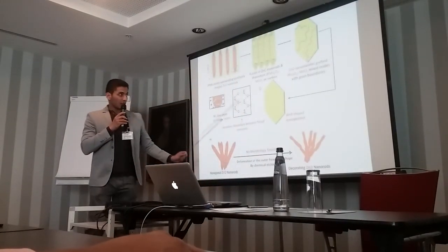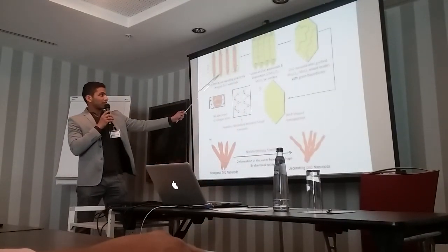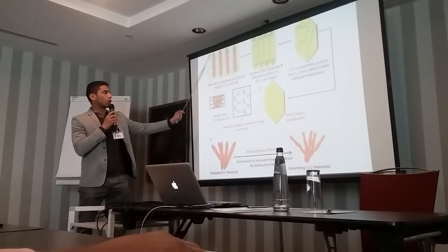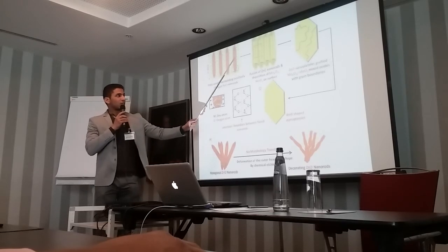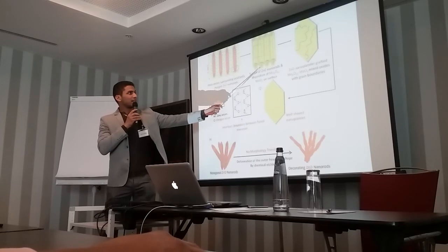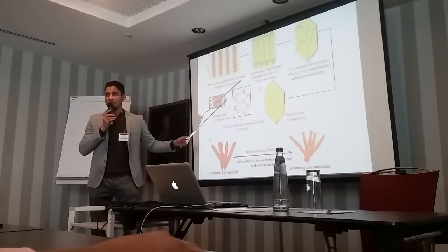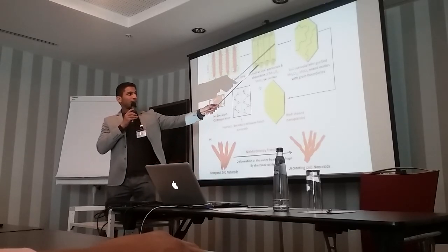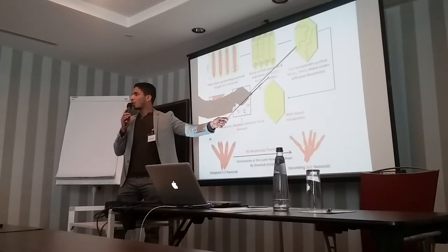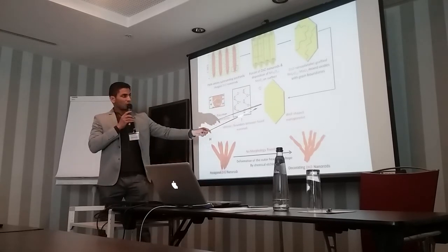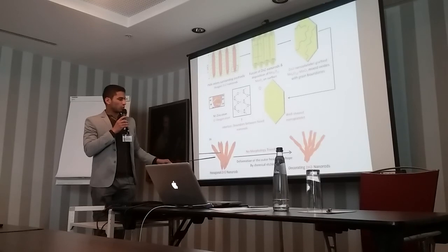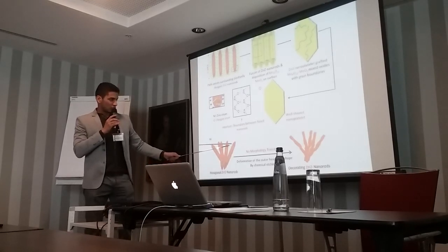In a simple way, we started with zinc oxide nanorods immersed in polyoxometallate solution, or phosphomolybdic acid. Then we noticed the formation of cross-linked zinc oxide nanostructures. Over time, the formation of hybrid nanoplatelets, but with grain boundaries, no complete fusion. At the end, we got these well-shaped nanoplatelets. At the same time, we noticed only chemical etching of some zinc